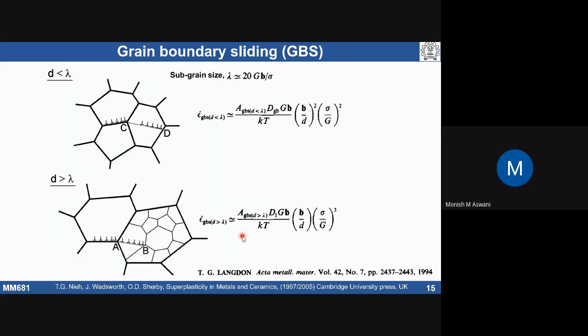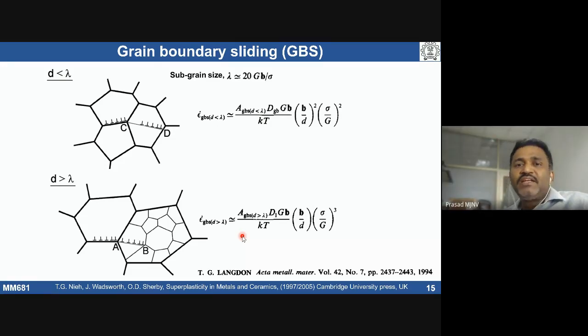So why did you say we'll go for case 1 and not case 2? Because most superplastic materials have a requirement of less than 10 micrometer grain size. If I calculate for a particular material at a particular stress, where the superplastic stress is very low, then your lambda, the subgrain size, is going to be coarser than 10 micrometers. Subgrain size is going to be coarser than 10 micrometer grain size at low stresses.